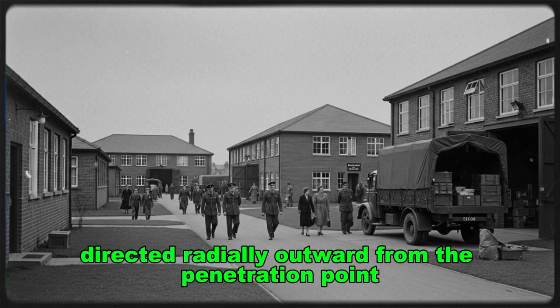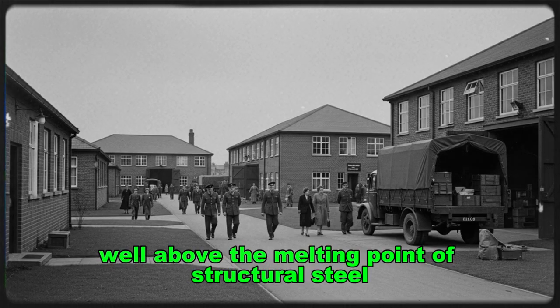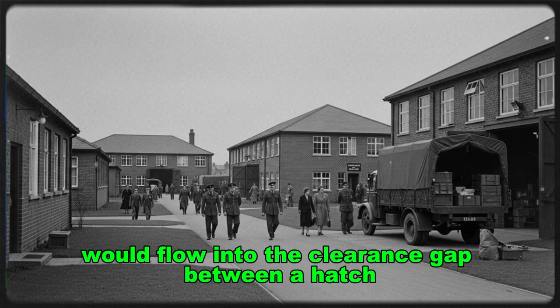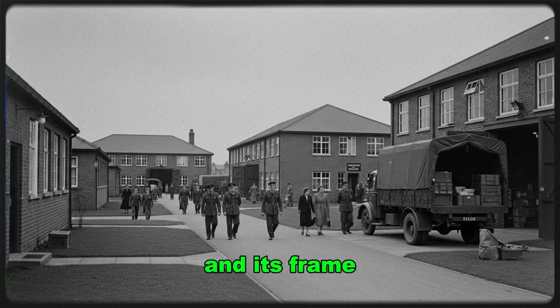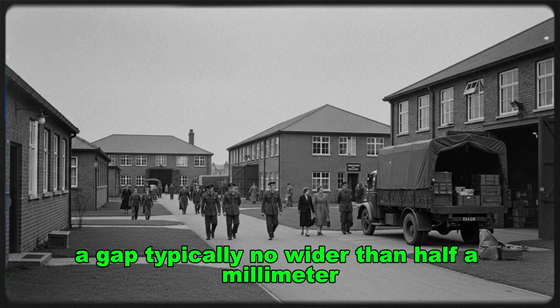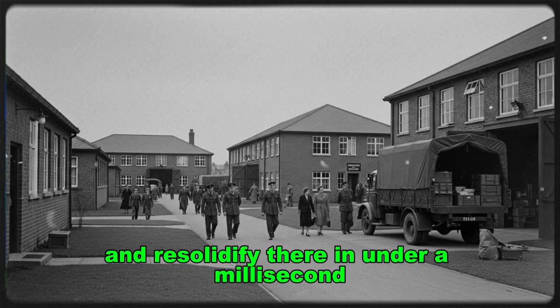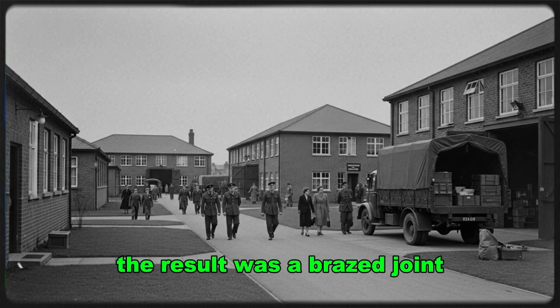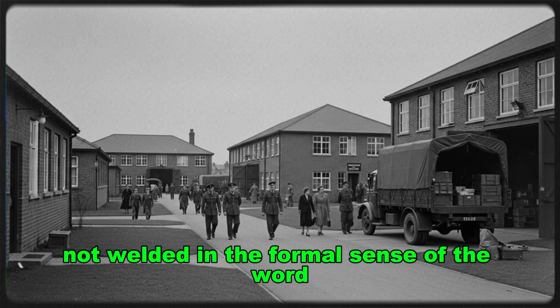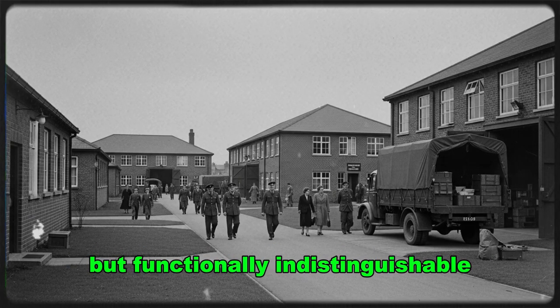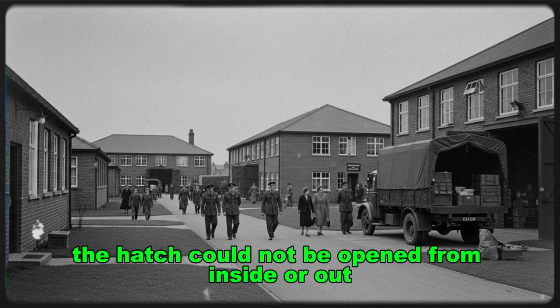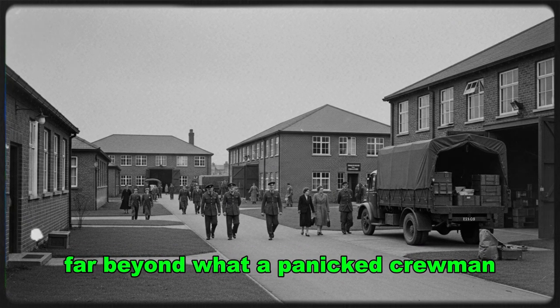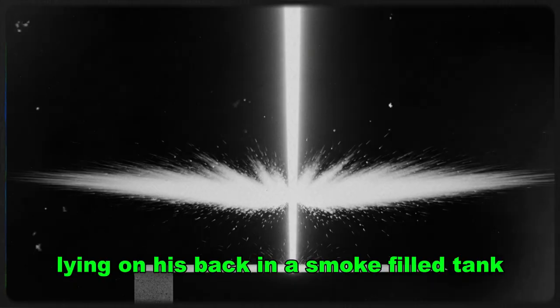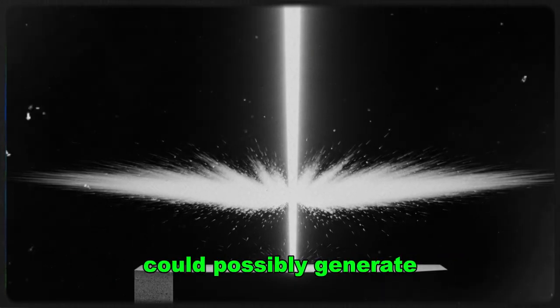The copper-rich splash, directed radially outward from the penetration point at temperatures well above the melting point of structural steel, would flow into the clearance gap between a hatch and its frame, a gap typically no wider than half a millimeter, and resolidify there in under a millisecond. The result was a brazed joint, not welded in the formal sense of the word, but functionally indistinguishable. The hatch could not be opened from inside or out without applied force, far beyond what a panicked crewman, lying on his back in a smoke-filled tank, could possibly generate.